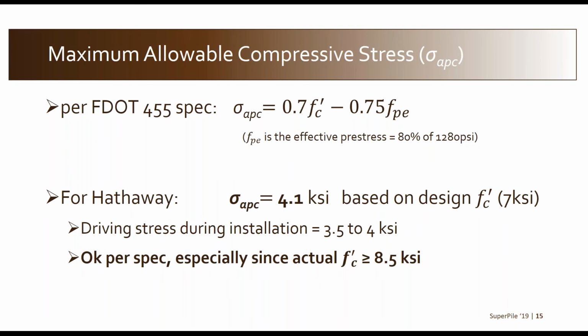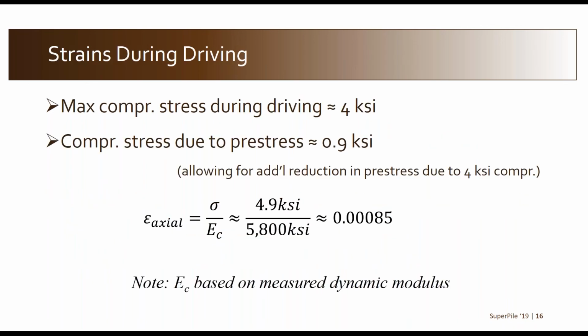So that's a function of the compressive strength of the concrete and then also the effective pre-stressing force. It comes out to just over 4 KSI for the properties of the piles on this job using the design compressive strength. The measured driving stresses during installation were below that, ranged between 3.5 to 4 KSI. So per the spec, these piles were fine. And you would be led to believe, if you believe that the spec is reality, that there shouldn't be any damage, especially since the actual concrete strength was 8.5 KSI on average, so higher than the nominal compressive strength.